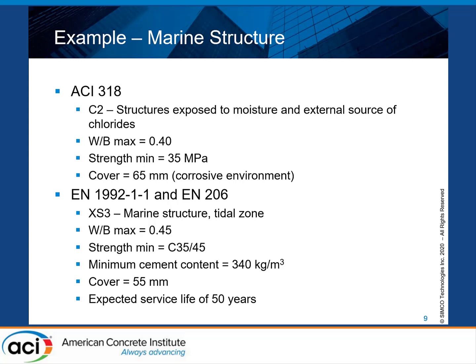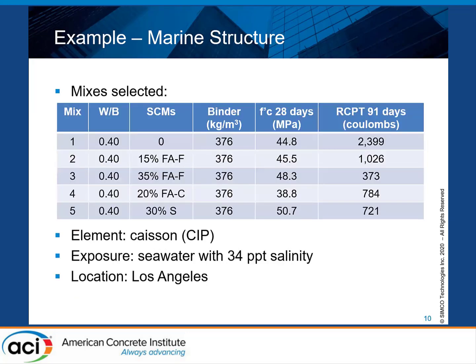The maximum water binder ratio in that case is 0.45. The minimum strength is 35 MPa, and they have a requirement for minimum cement content of 340 kilograms per cubic meter, minimum cover 55 for that particular case, and this is supposed to give me 50 years of service life. If I want to go to 100 years, then the cover would have to be increased, but I decided to use the basic example.